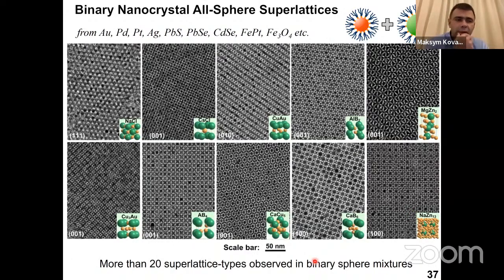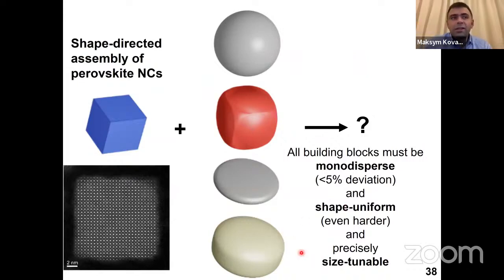And so in our work, we set out to ask ourselves, okay, we have cubic shaped nanocrystals. Will that matter? And then you look in the literature and you find that nobody actually ever made binary lattices where you mix non-spherical nanocrystals, particularly cubic ones. And so I have brilliant students, and one of them, Igor Chernyuk, has done titanic work, first producing the library of these shapes with extreme control of the monodispersity: cubes, spheres, truncated cubes, disks, thin disks, thick disks, and he combined cubes with all kinds of other nanocrystals, trying to build multi-component superlattices. It's basically at the limits of what synthetic chemistry can do at the mesoscale.